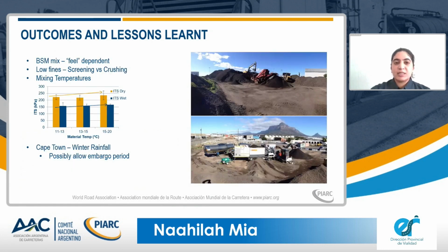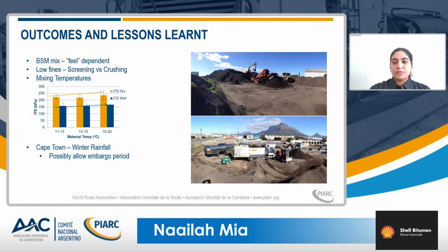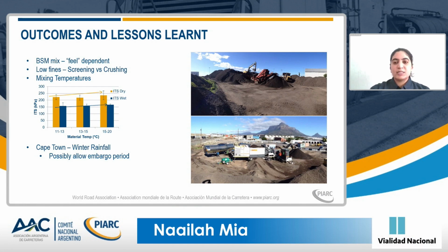The outcomes and lessons learned with regards to this project. The BSM mix is very feel dependent, so we needed to pay close attention to the moisture content, and you needed somebody on site with some experience with BSM to determine whether the moisture content was correct. Low fines: due to the fact that this was more on the coarse side of the grading envelope, we had low fines. We looked at crushing or screening to consider that.